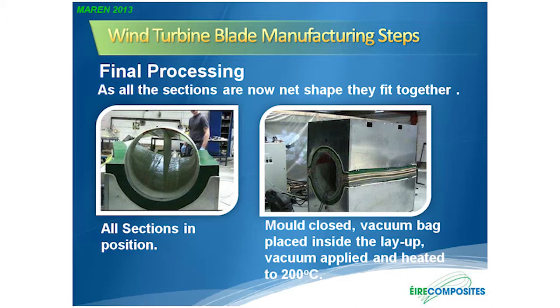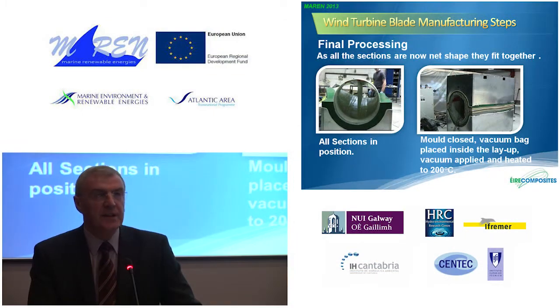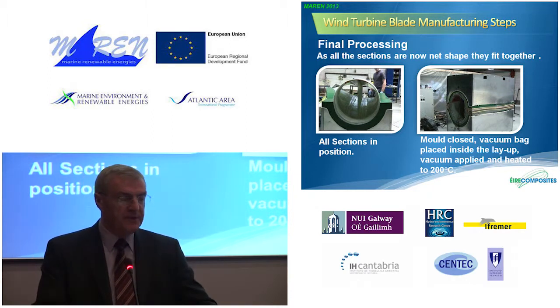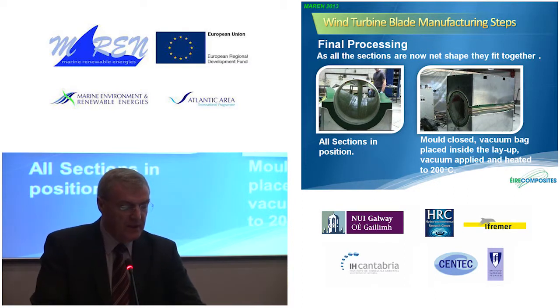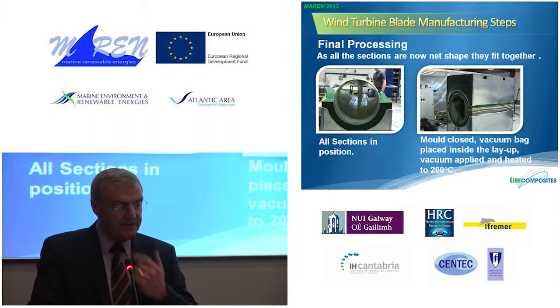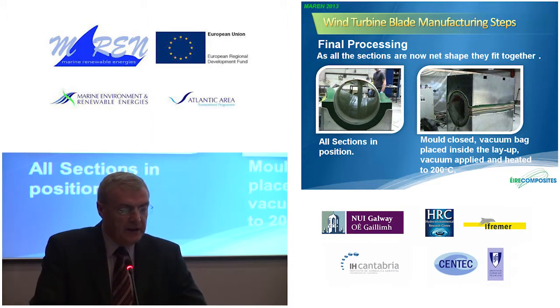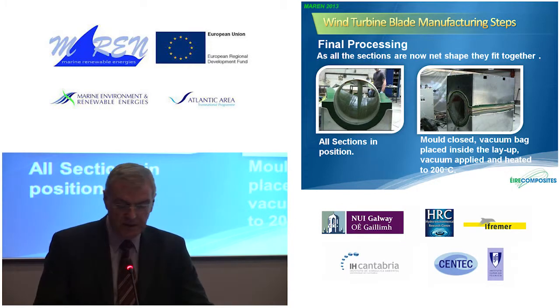is that basically the mold or the blade has been reassembled, and all the component parts of it are fit together like a jigsaw. There are no gaps or any joints in the mold or in the product at that stage. The final step is to place a vacuum bag inside, heat it up to 200 degrees and cool it down.